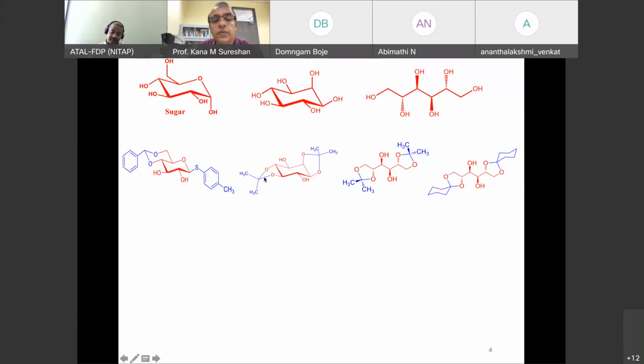Similarly, in inositol, you can put two acetone molecules and make this diacetonide, or you can say diketal. And similarly, here two molecules of acetone were added to get this diketal. This is mannitol diketal. Also, another ketone we have added here, cyclohexanone, to make this cyclohexyl ketal. So these are all amphiphilic molecules now, partially hydrophilic, partially hydrophobic. Now they are soluble in some non-polar solvents. Still they have hydrogen bonding possibility because there are OH groups still left there. So they can form a hydrogen bonded network in a non-polar solvent.